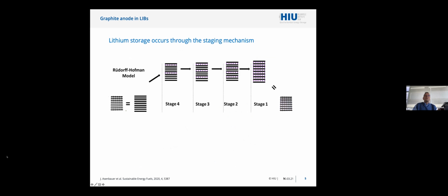So how does it work? A little bit on the mechanism. It has been demonstrated that actually the lithium storage in graphite occurs through what is called the staging mechanism. So lithium is not stored uniformly between all layers, but it tends to actually fill few layers once in a while, and then the more lithium we put in, the more layers are filled.